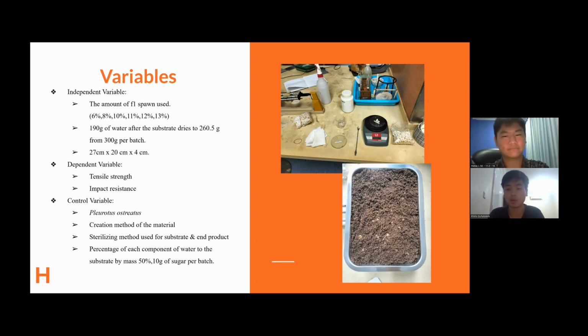The creation method was previously mentioned. The sterilization method is just putting it in an oven for a certain period of time at a certain temperature to kill the mushroom. And the percentage of water to substrate is 50%, like previously mentioned in the independent variable, and 10% of sugar used per batch.